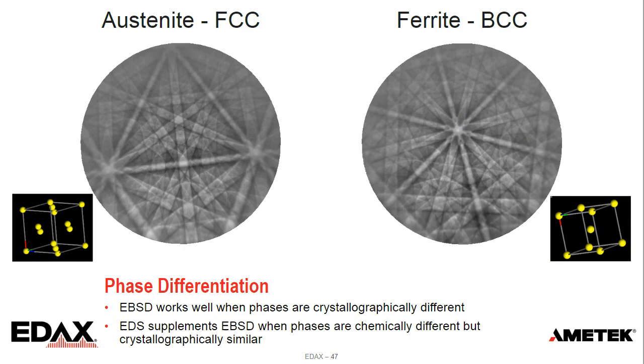Ferrite is body-centered cubic, or BCC. They're very distinct crystallographically. So what that means is that the projection of the planes that diffract, the projection of those planes onto the EBSD detector, are different. For EBSD, for our Hough-based indexing, we're measuring the angles between these planes. So if different planes are diffracting, angles are different, it's very easy to tell these different phases apart. When structures start to become more crystallographically similar, that's when EDS can supplement EBSD.